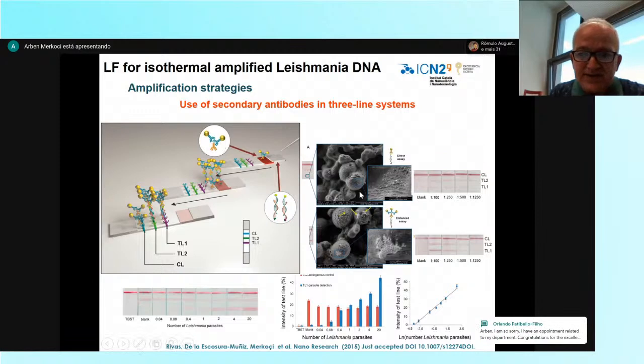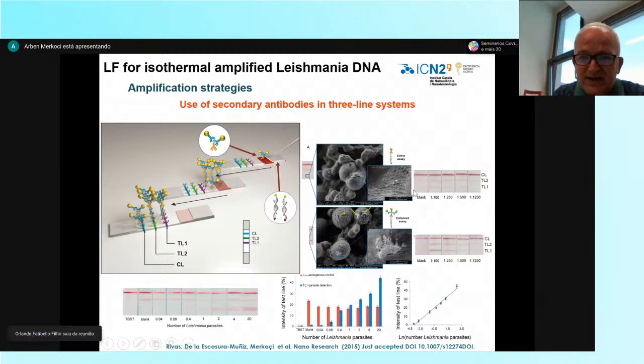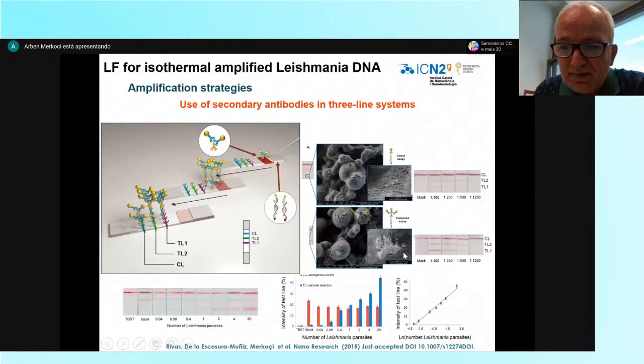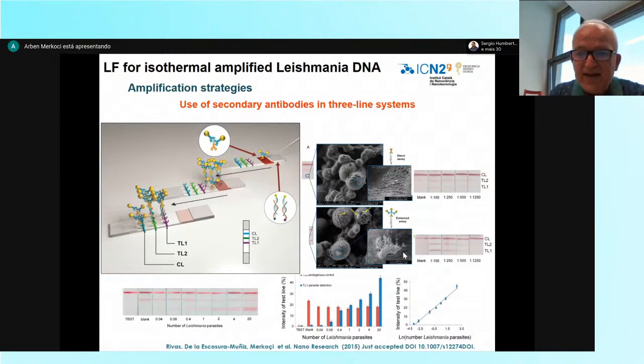You can see here, for example, what happened with the system without amplification. You can see just a few gold nanoparticles here in the detection line. But in the case of the enhanced assay, where a secondary antibody with gold nanoparticles is used, a big accumulation of gold nanoparticles is appearing, as you see here from these images. And in fact, you can see clearly here the change of the geometry.